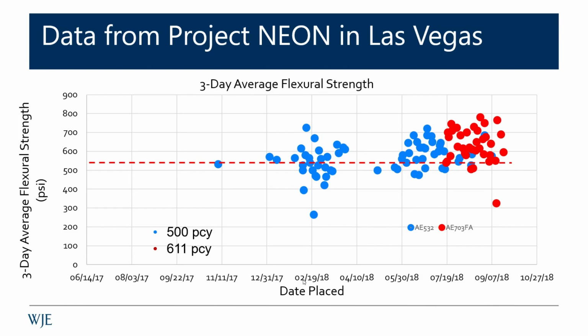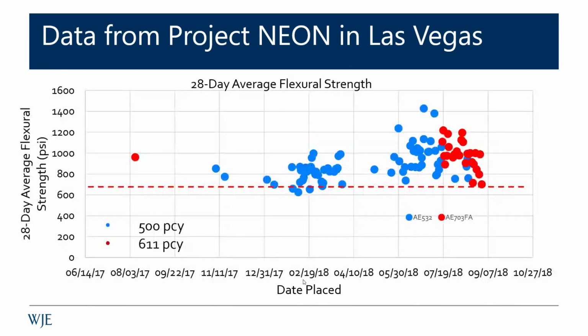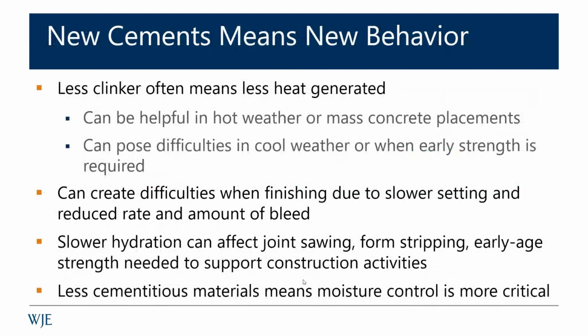But at the 28 days flex strengths, you can see they're all really, really good. And if you notice where they're really, really high. So the one thing to remember though, as we switch to new cements and new mixes, it is going to lead to different behavior. Anytime you're switching a cement source, you should expect the behavior to be different. It's just that we have become so accustomed to those few cement sources that we have that now when a change happens, all of a sudden it causes the whole system to kind of come off the rails a little bit.